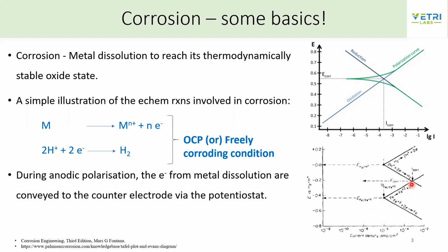So if we draw these curves based on the slopes, then we end up with an intersection point, which is the corrosion current density and the corrosion potential that we see in a potentiostat. So this is the mixed potential theory.